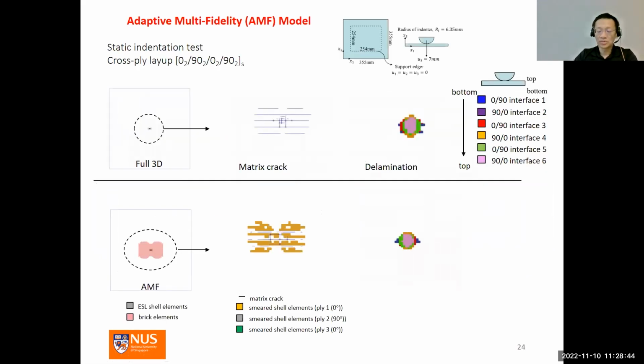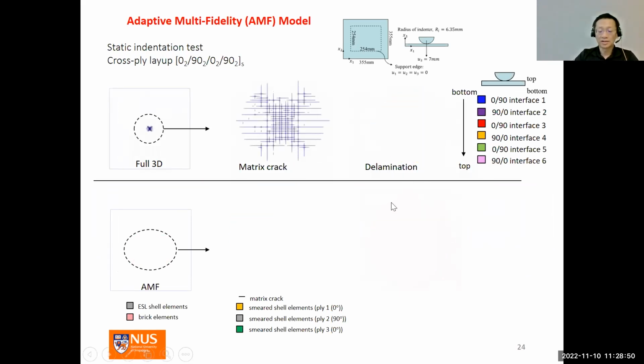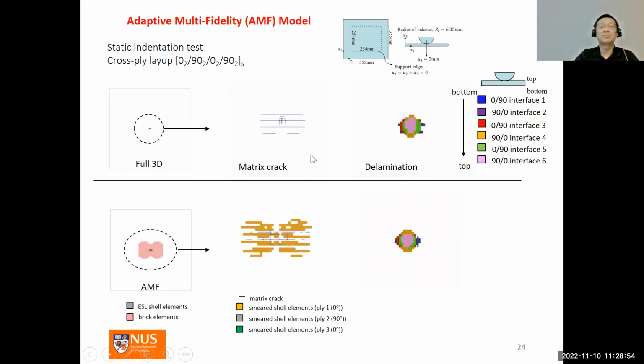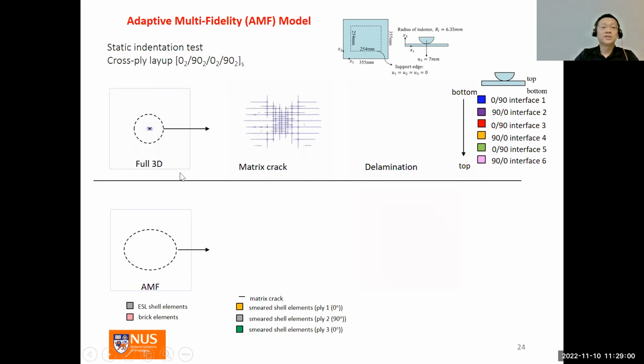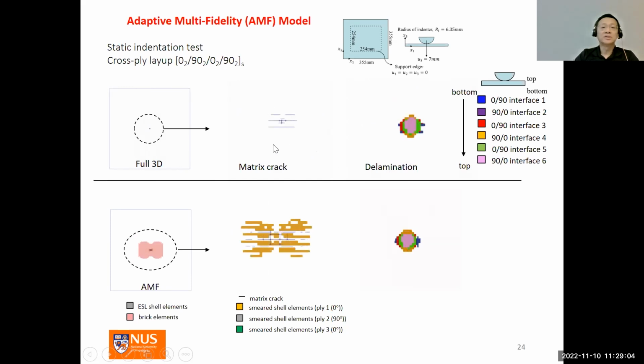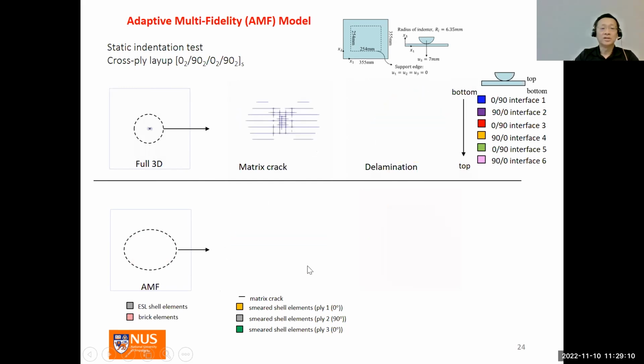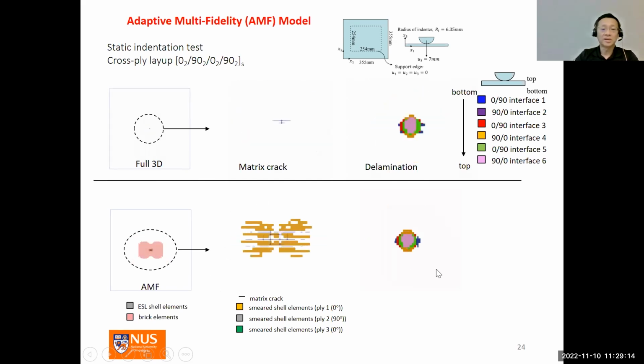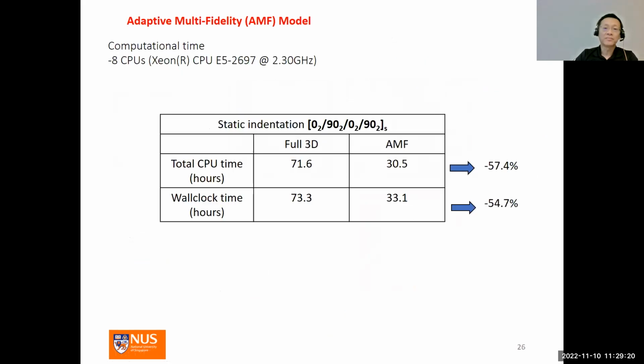So we have been applying this multi-fidelity model to static indentation. For example, here, this is a problem with static indentation. So the top picture here is a full 3D discrete crack model with the matrix cracks here, and then the delamination prediction. And then the lower one is the adaptive multi-fidelity prediction. And the savings in computational time for these models here is a little bit more, about 50%.